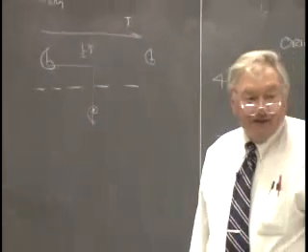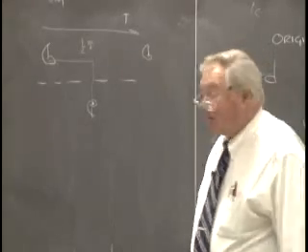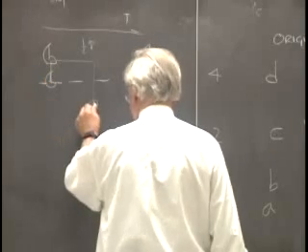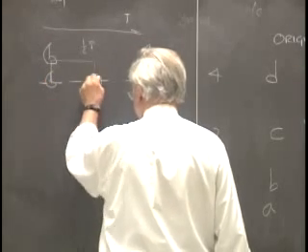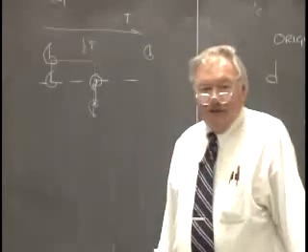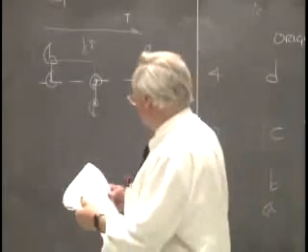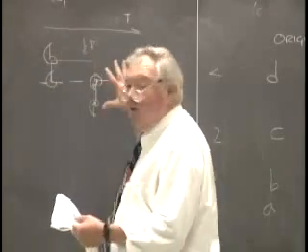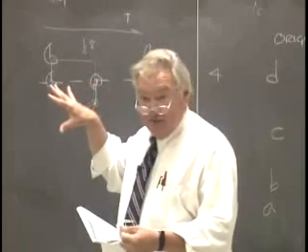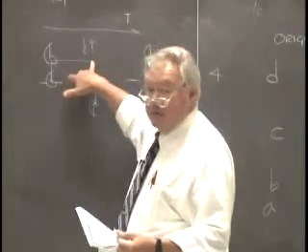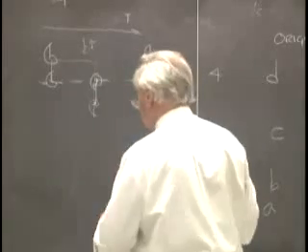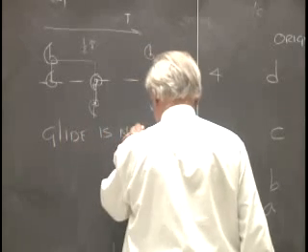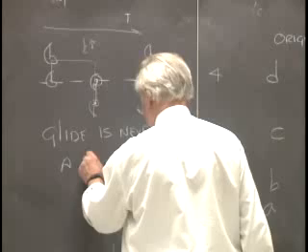What happens if I let the atom migrate onto the glide plane? Let this atom move down to here. Now it sits here. This one, repeated from it by glide, will migrate up to here. Nothing happens. It's just that the amount that the atom is displaced from the locus of the glide plane is different in the 2 cases, but there is no coalescence of the atoms because of this translation component to the glide plane. So a conclusion then is that glide is never a candidate location for a special position.